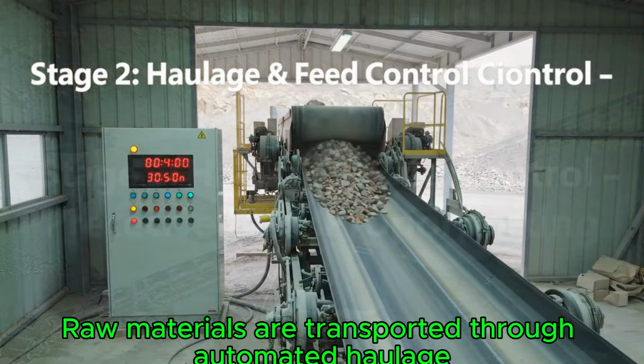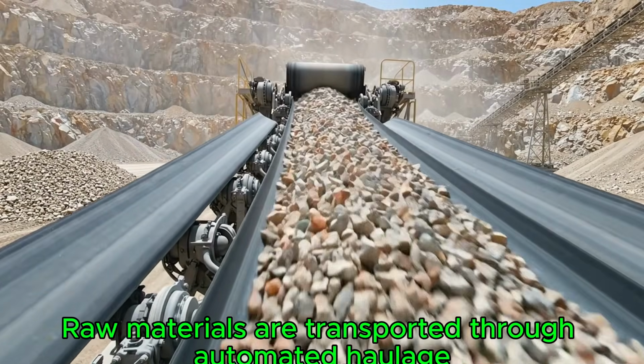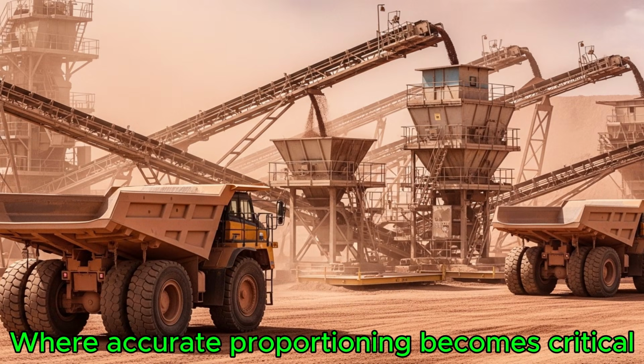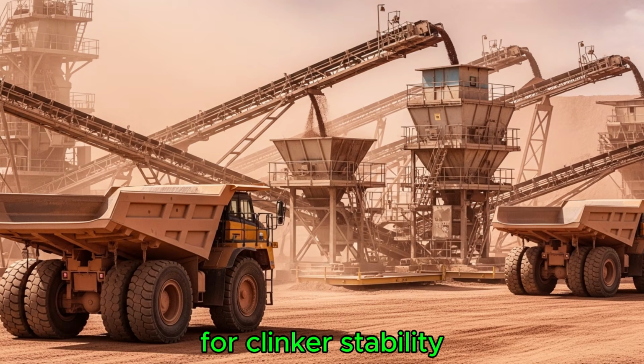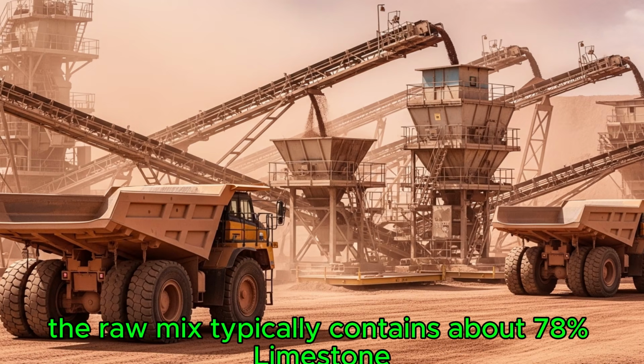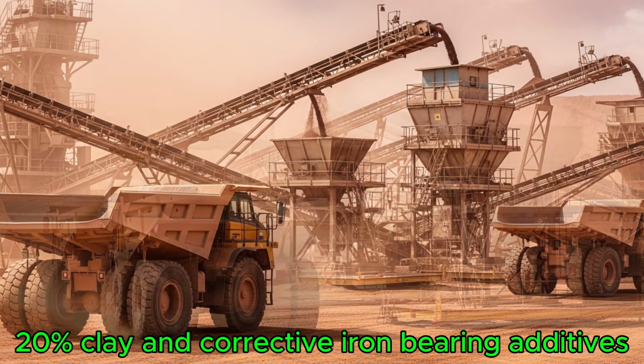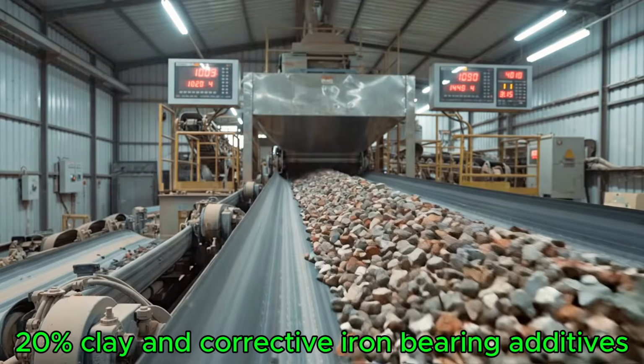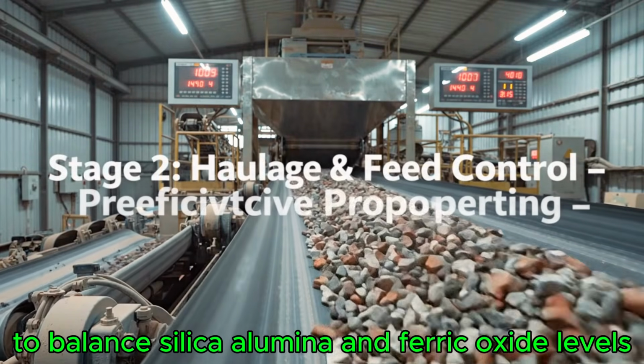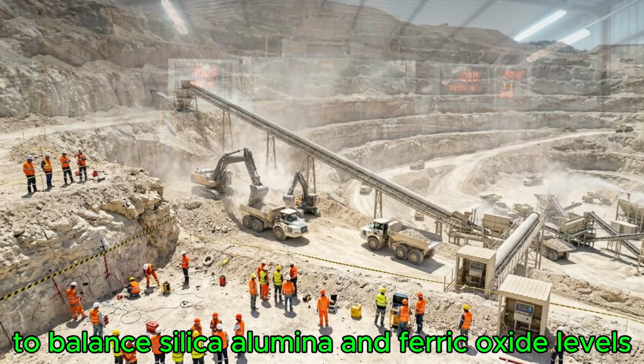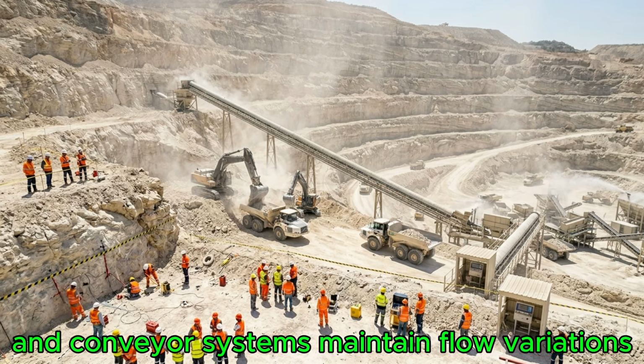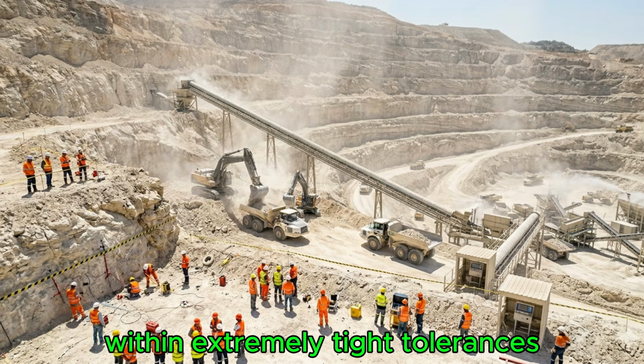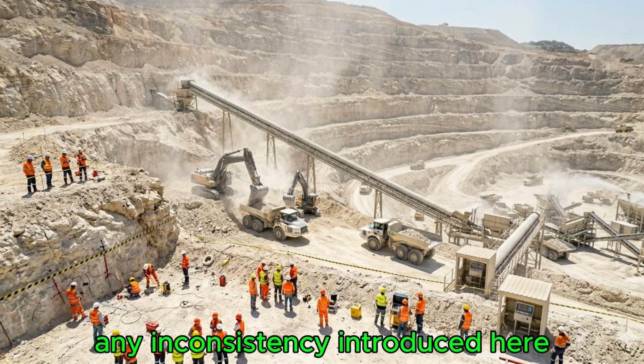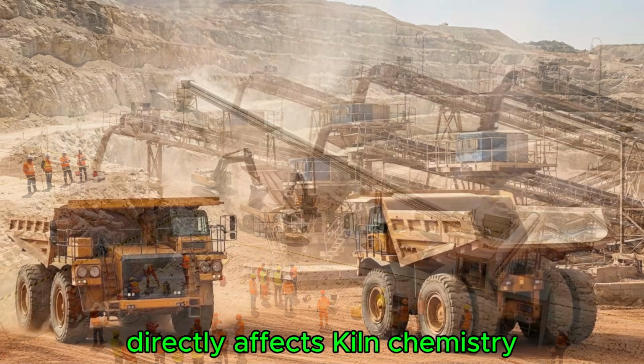After extraction, raw materials are transported through automated haulage and feed systems where accurate proportioning becomes critical for clinker stability. The raw mix typically contains about 78% limestone, 20% clay, and corrective iron-bearing additives to balance silica, alumina, and ferric oxide levels. Automated weigh feeders and conveyor systems maintain flow variations within extremely tight tolerances. Any inconsistency introduced here directly affects kiln chemistry several hours later due to the continuous process cycle.